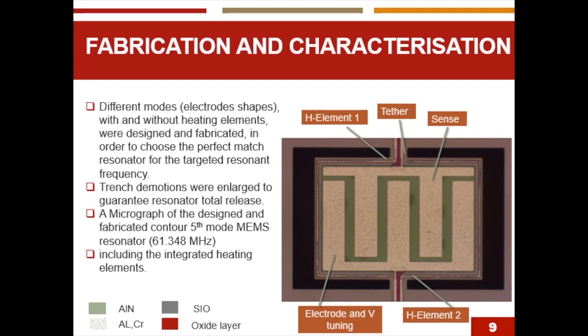As we can see here, it's very clear to recognize the electrode. Also we can see the tethers and the heating elements from both sides, and the SOI layer around the resonator. And aluminum nitride layer, the piezoelectric in green underneath the electrode and sense. And this is the oxide layer here on both sides. The black area is the trench cavity. This time we made sure to enlarge the trench cavity enough in order to guarantee a total release for the resonators.